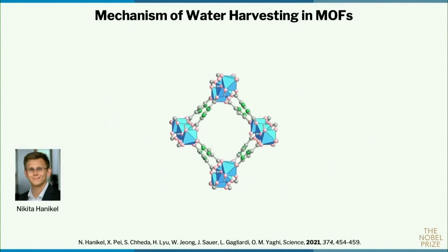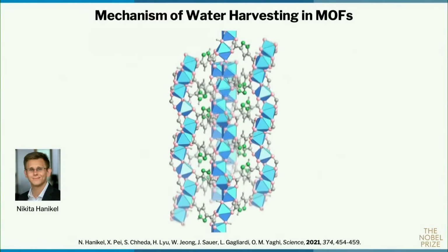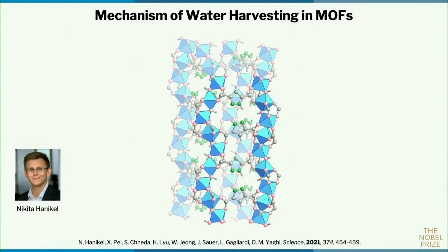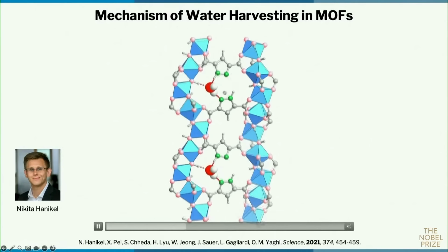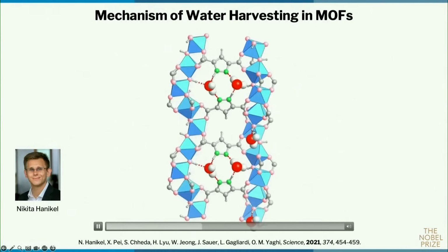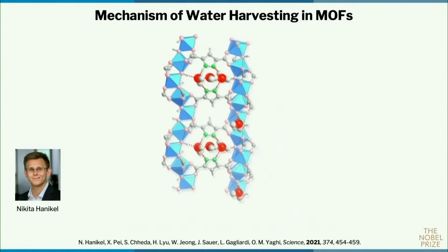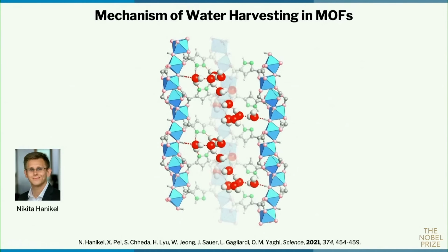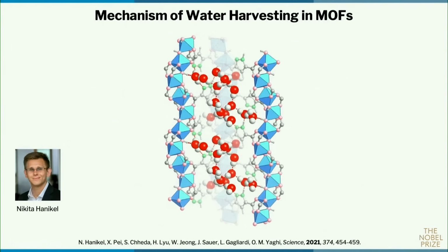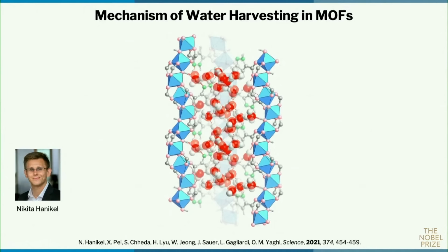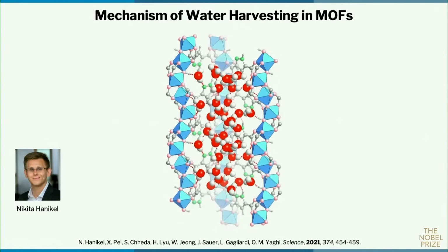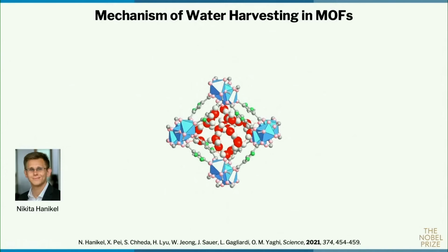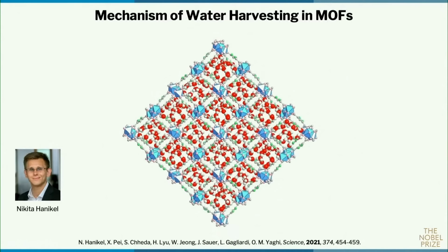What you see is that the first water molecules obviously go to the most hydrophilic, water-loving sites. And then once those sites are filled, they bridge over the hydrophobic sites. So in the interior of the structure, if I was a water molecule floating inside the pore, I'd see a grid around me of hydrophilic, hydrophobic, hydrophilic, hydrophobic.